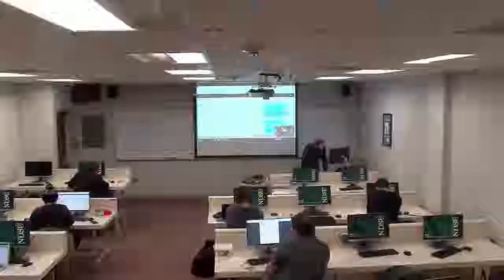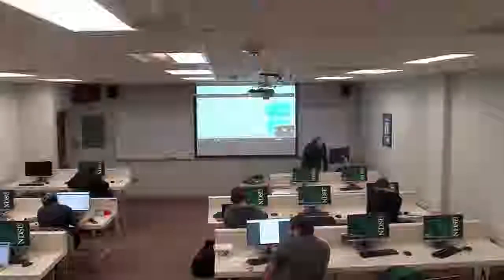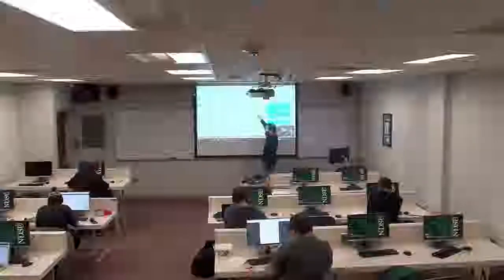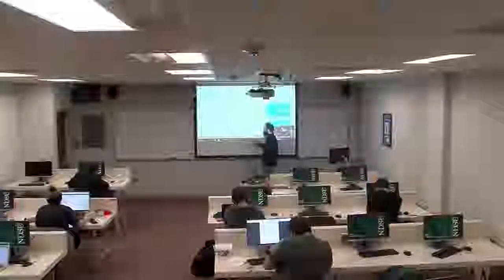I don't have enough room to squeeze all of this stuff in, so I have this over here for now. This is my plot of relaxation times for these systems as a function of dissipation energy. What I mean by dissipation energy is, in the case of electrons, the energy difference between the photoexcited state and the LUMO. In the case of holes, it would be the energy difference between the HOMO and the photoexcited state of the hole, the state that the electron left upon photoexcitation.